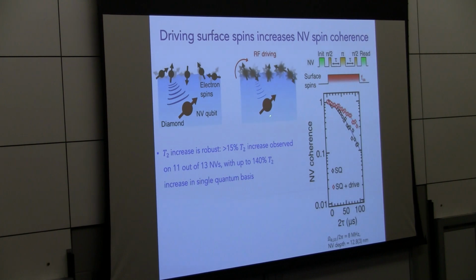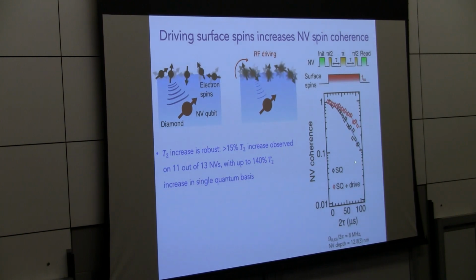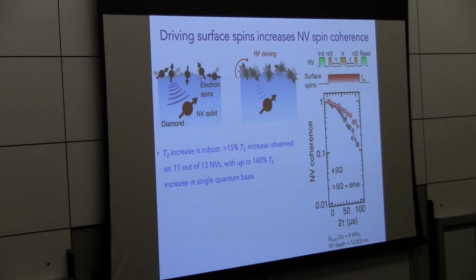That's what we've done: we've measured the T2 of the NV center as we drive these surface spins, which are at a different frequency. This is a plot of NV T2 without driving, and the red is with driving. We did this for several NVs, and the T2 is always increased up to more than a factor of 2.